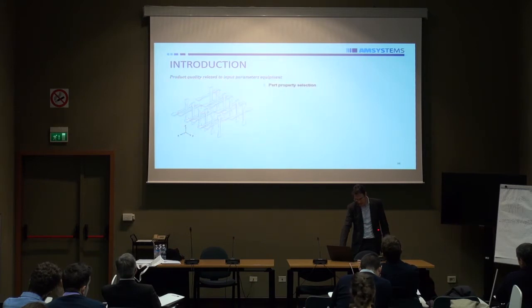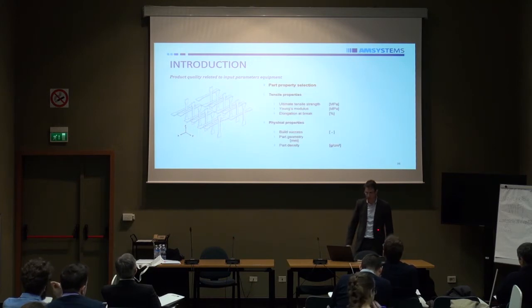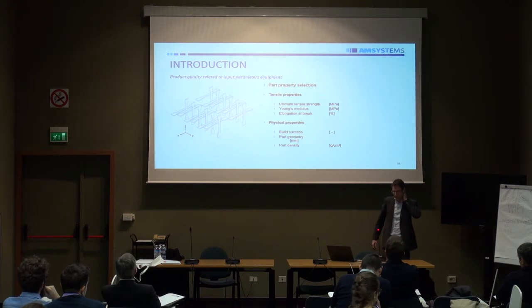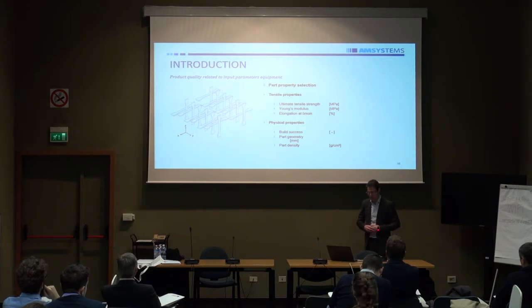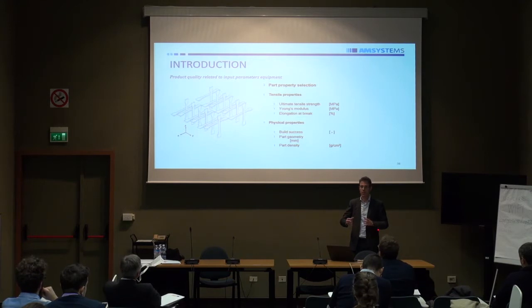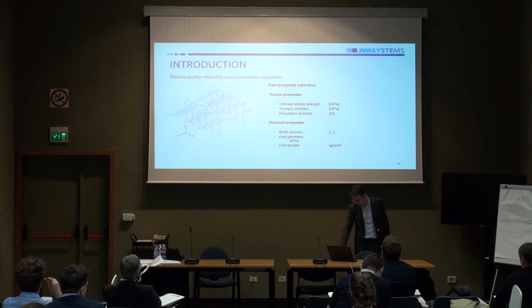And so how to measure these quality differences? We already did some work with making a lot of tensile bars. And there you can measure, for example, the tensile strength. You can measure the Young's modulus, the elongation at break. Of course, even at the current state of technology, it can be a failure that the build just didn't work. Is your part geometry accurate? And is the density correct?